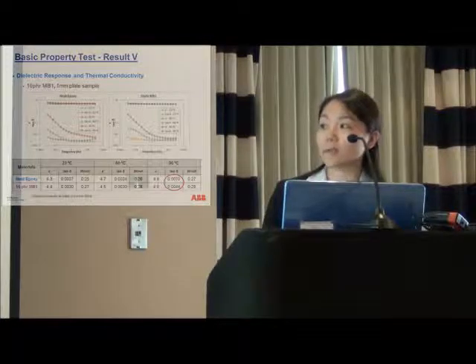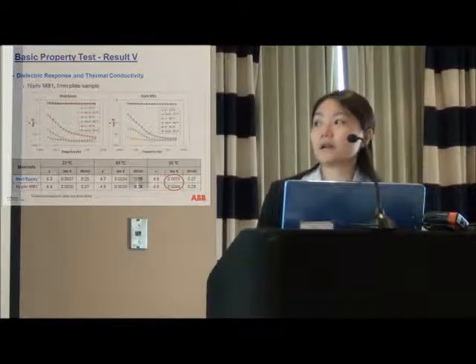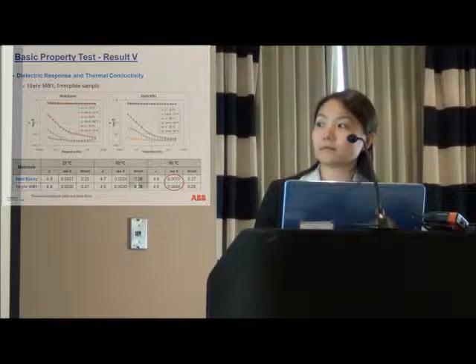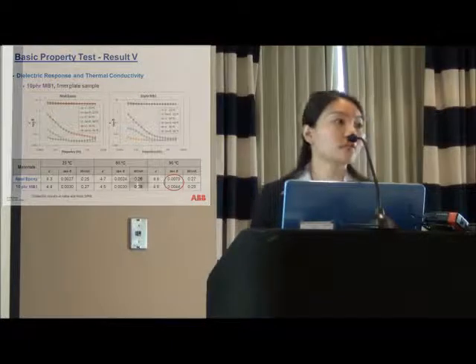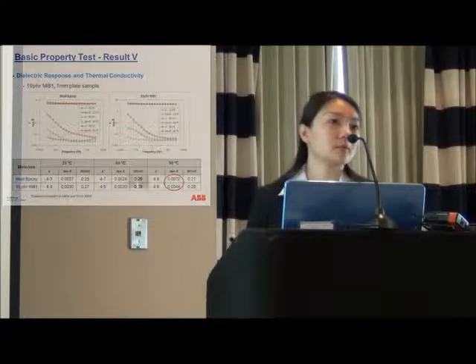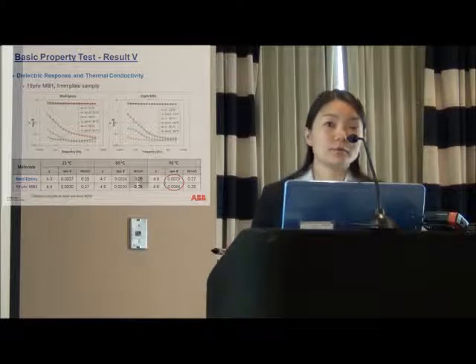And also we checked the thermal conductivity. There was no surprise by adding 10 pHr particles - the thermal conductivity of the matrix increased linearly, and there was no nanometric effect. It was the same as the micron fillers, and it's more or less a rule of mixture increase of the thermal conductivity.